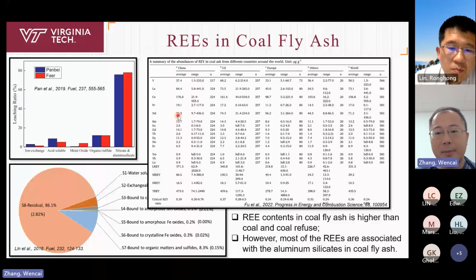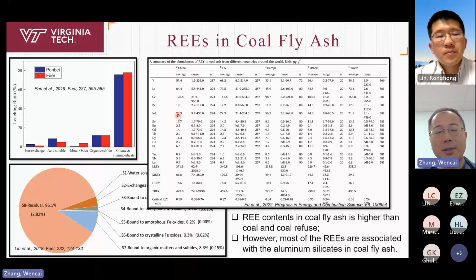However, as I mentioned at the beginning of this presentation, compared with coal, the organic matter in coal has already been removed, so the rare earth concentration in coal ash and coal fly ash is much higher than in the coal. So it is still worthwhile to evaluate and develop some technology for rare earth recovery from coal fly ash. The content of rare earth in coal fly ash is around 500 ppm level, which is much higher than the coal, which is only 70 ppm level.